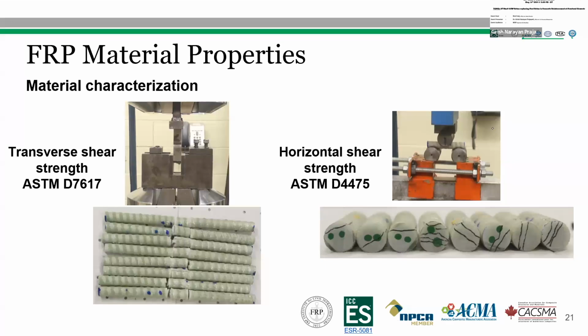The transverse shear strength and the horizontal shear strength of the GFRP bar were tested using an MTS universal testing machine. The displacement rate was selected to produce failure within 1 to 10 minutes, and the force was applied uniformly without subjecting the specimen to impact.